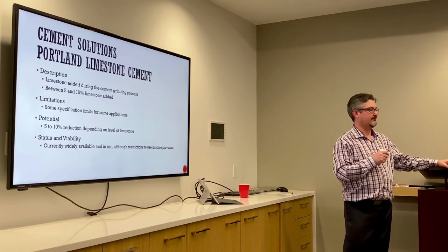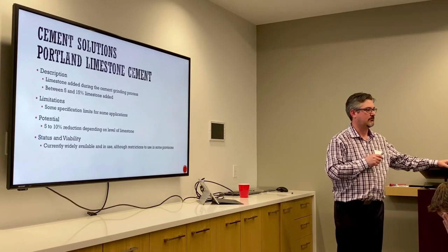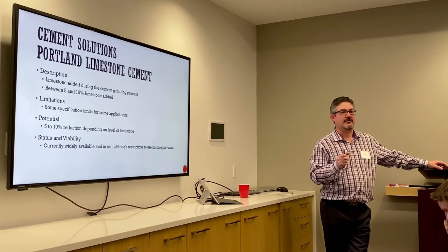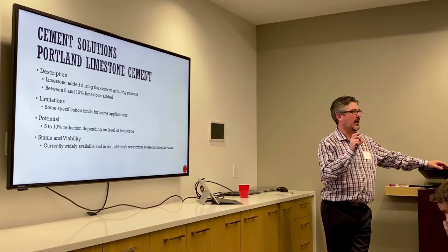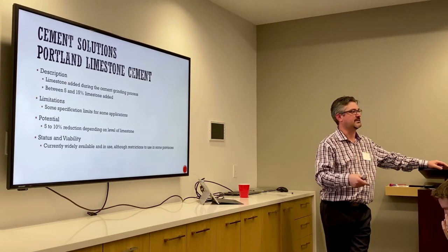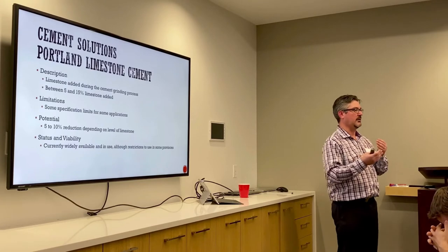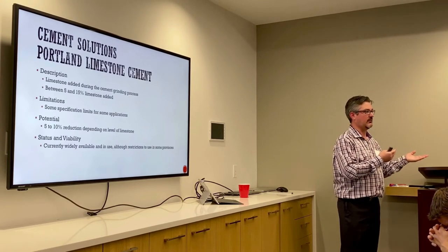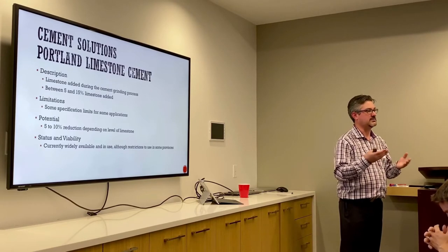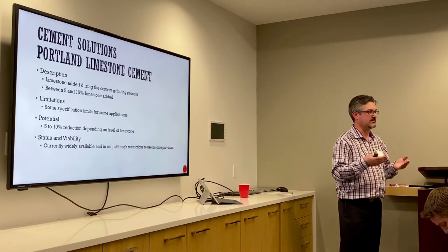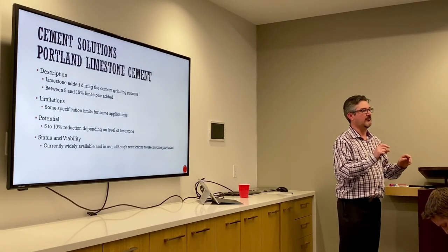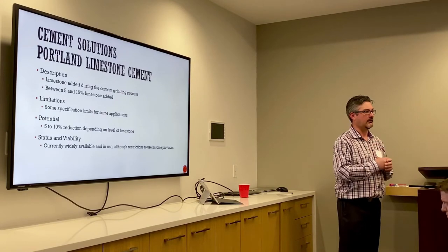So what are the side effects of adding limestone afterwards? The way it's actually produced in Canada is that the cement has what we call equivalent performance. So a ready mix producer should be able to swap between GU cement or type 1 cement and GUL cement or type 1L cement without making significant changes to their operations. The strength of the concrete is the same. That equivalent performance was based on 28-day strength.